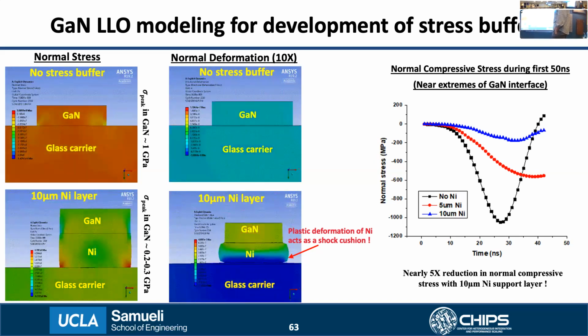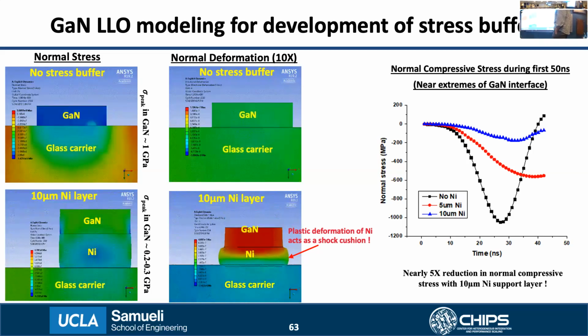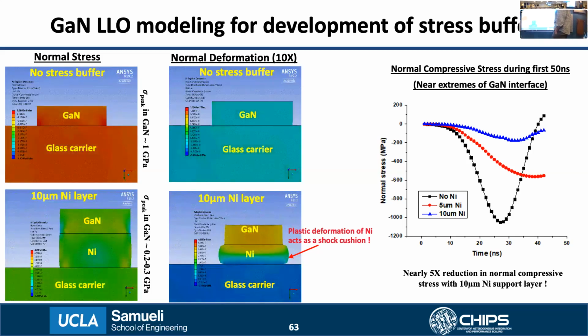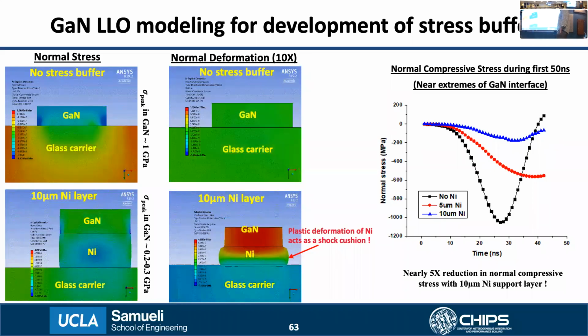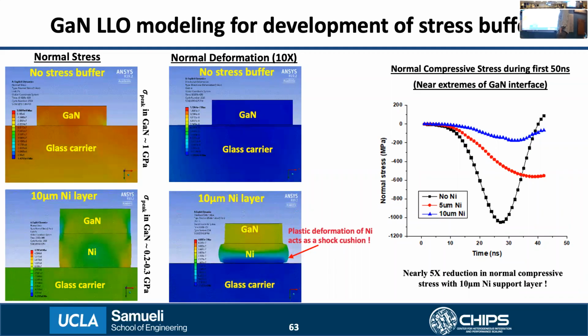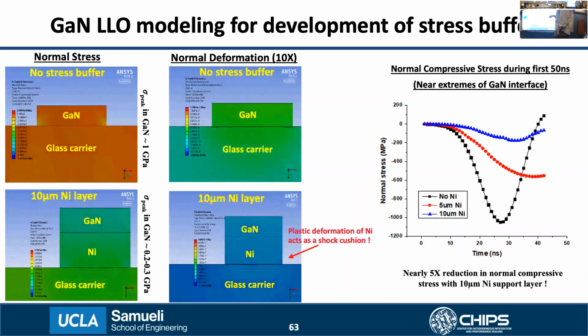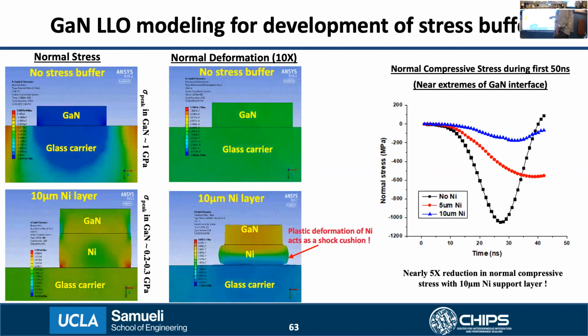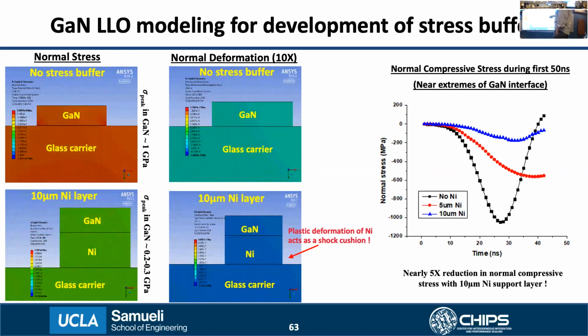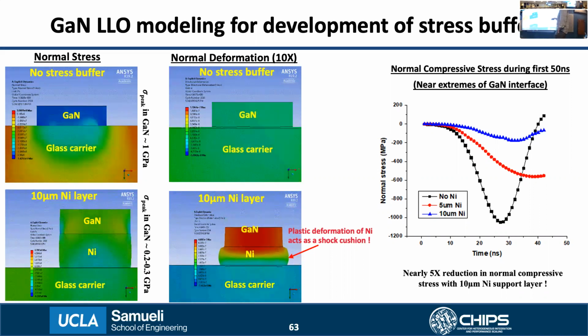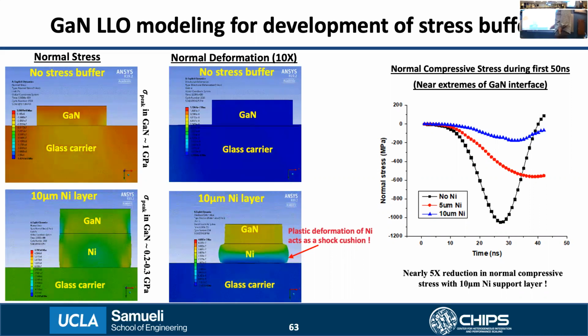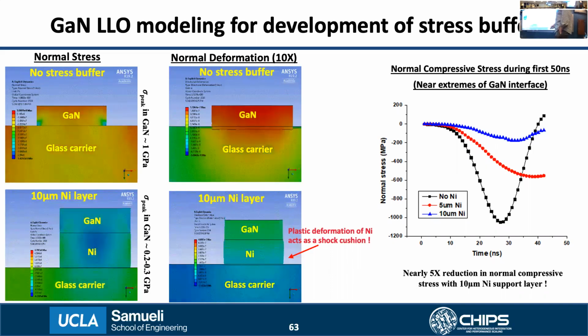I see. And did you try to use continuity kind of conditions? How would that be different from fixing the glass carrier? Or are you thinking about the thickness of the glass below? Yes, if it's thin, I see that fixing it could maybe make sense. So I've shown a zoomed in view. The glass carrier was assumed to be around 700 microns thick, and the bottom of that was fixed. I see.